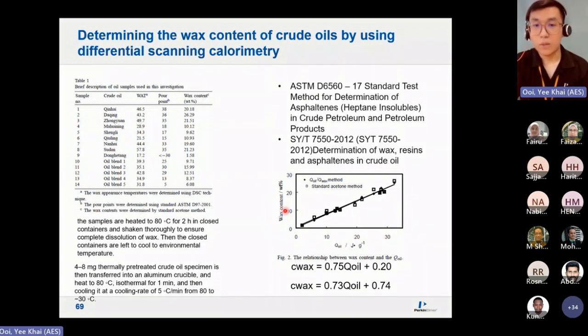From here, wax content versus the peak area of the crystallization peak, you can plot a calibration curve. Next, you can run an unknown crude oil to determine how much wax content is present, using this calibration. So when calibrations are involved, quantitation is required. With a standard of known wax content, you plot a calibration curve using DSC based on the peak area, joule per gram, the enthalpy of the crystallization peak.